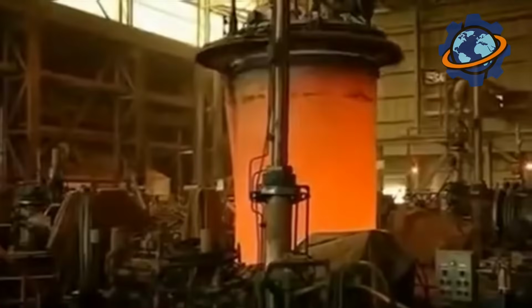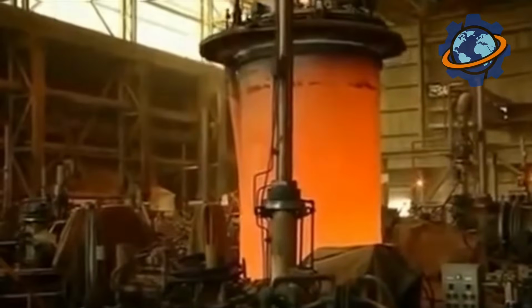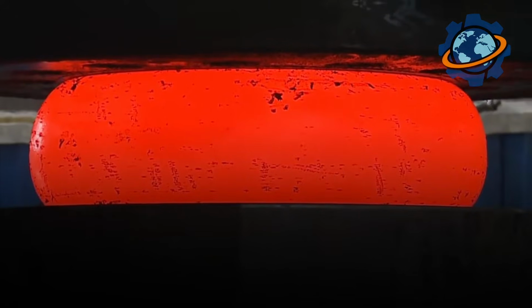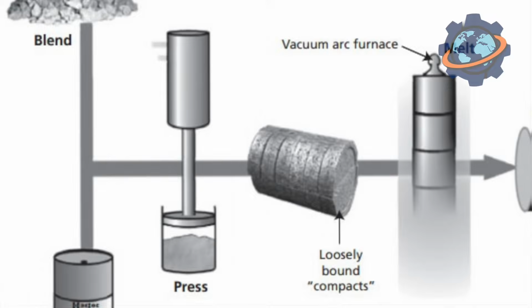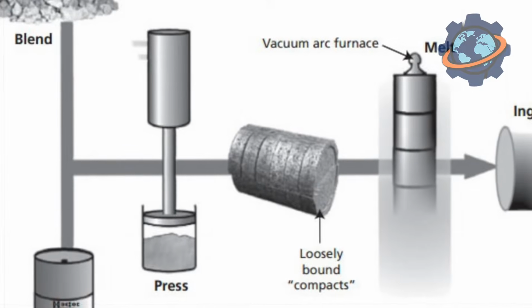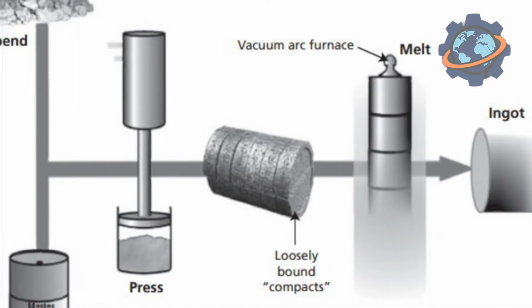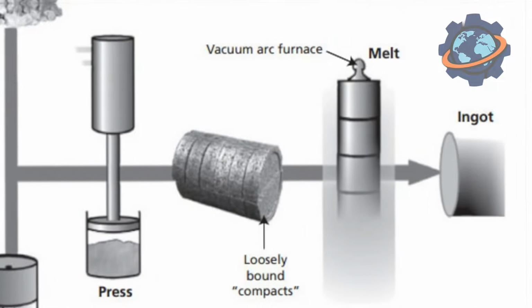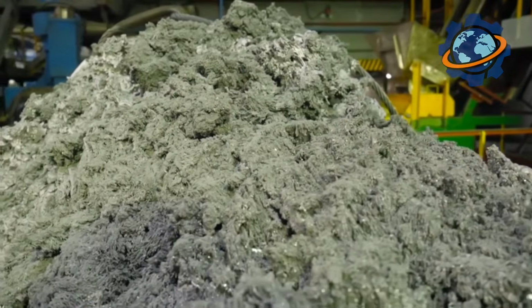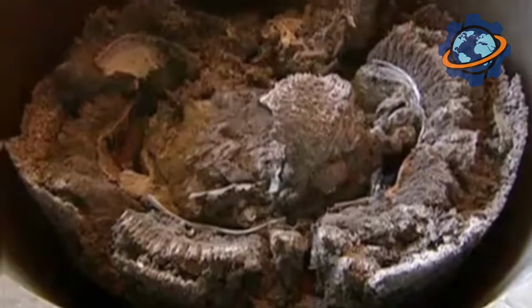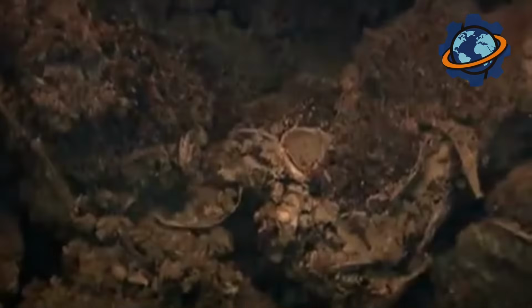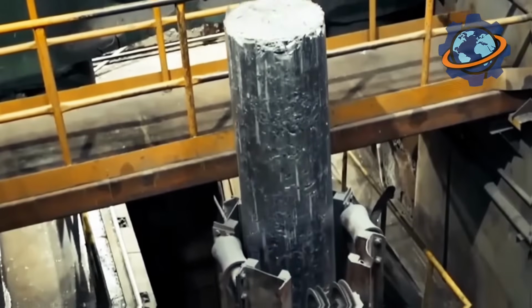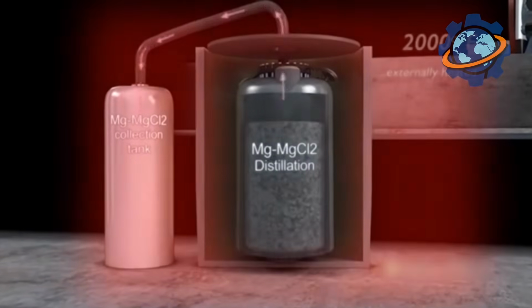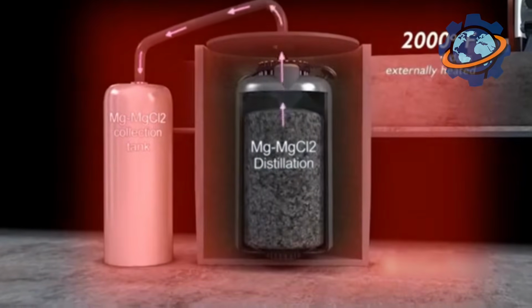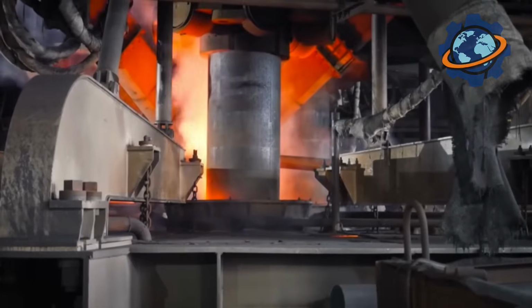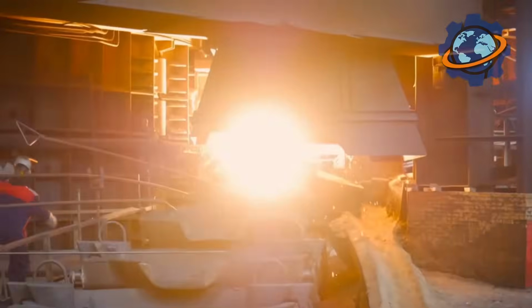The next key stage is the reduction of titanium tetrachloride to metallic titanium. The most common industrial method is the Kroll process, in which titanium tetrachloride reacts with magnesium in a vacuum chamber at high temperature. The result is titanium sponge, a porous metallic powder containing impurities of magnesium and magnesium chlorides. This reaction mass is subjected to vacuum distillation to remove impurities, after which the titanium sponge is pressed and remelted into solid ingots or slabs.